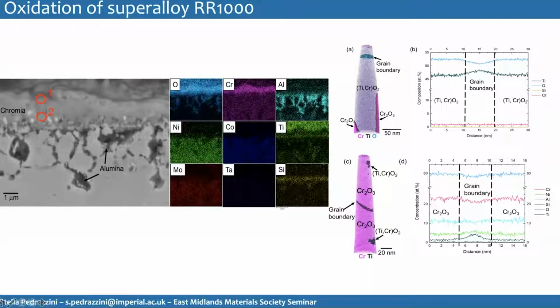So we have titanium and oxygen. Titanium is green, oxygen is blue. And this is a concentration profile going across the grain boundary here. I hope that people can see my cursor, because otherwise, can you see my cursor? I'm going to assume that you are seeing my cursor. Okay, so the titanium oxide, you can see the profile, and at the grain boundary, there's a slight depletion in oxygen and a slight increase in titanium content.